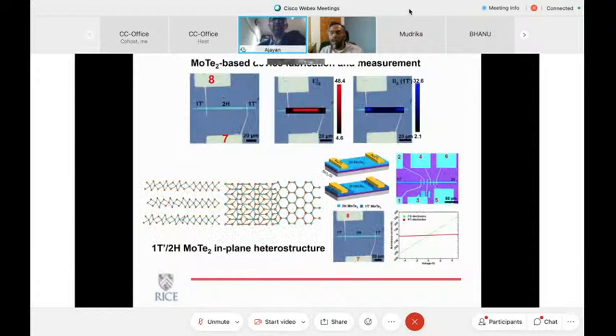And the reason why this was interesting is that people wanted to explore the semiconducting properties and a device based on the 2H MoTe2, but with 1T prime MoTe2 as a contact region. Like phase, you get a better ohmic contact. So, people did make some devices, but essentially it was just growing randomly and going and finding regions where the MoTe2 formed a metallic phase and then putting contact there.